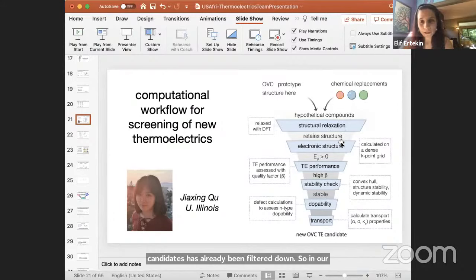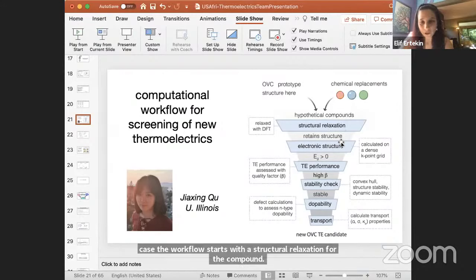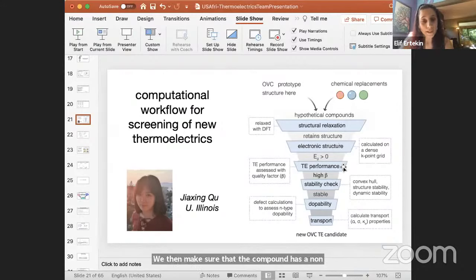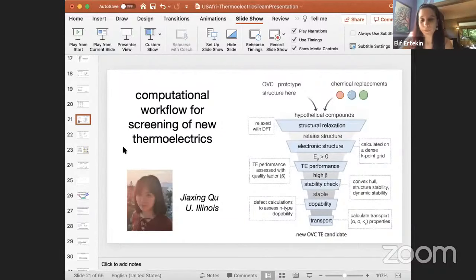We then make sure that the compound has a non-zero gap. We then assess its thermoelectric performance through the quality factor beta. The most promising candidates there are run through a convex hull analysis to determine their thermodynamic stability. And then the final most promising set of compounds are checked for their dopability.